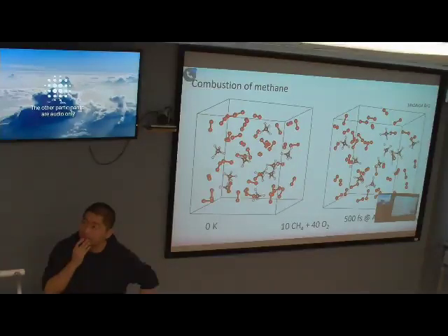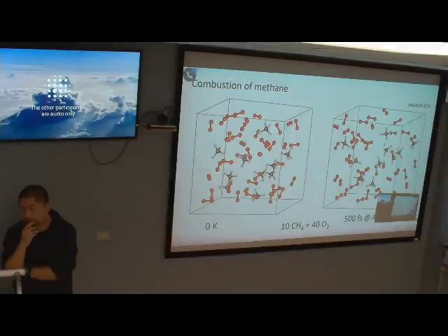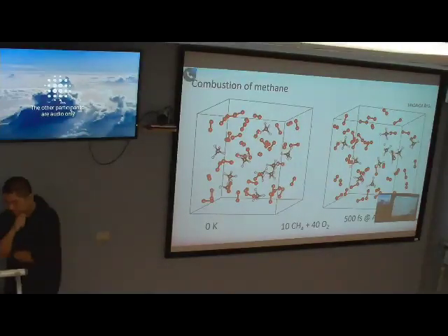Yes, but the temperature is also much higher. It's the frequency of collisions. If this density implies one collision per picosecond, then half a picosecond will never get to a reaction. And it is one of our approximations that we intentionally increase not only temperature but density to make them collide more frequently and explore these intermediates.